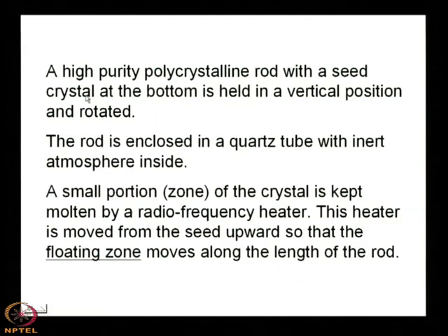Now, what is the necessity of a seed crystal? Why do we use a seed crystal for the growth of any crystal? Why is it required at all? Yes, basically we want a particular orientation of the crystal, 100, 111, 101, any particular orientation. So, there is a melt and it crystallizes by solidification, and during solidification if you introduce one seed crystal, the crystallization takes place in a better way with a particular orientation.